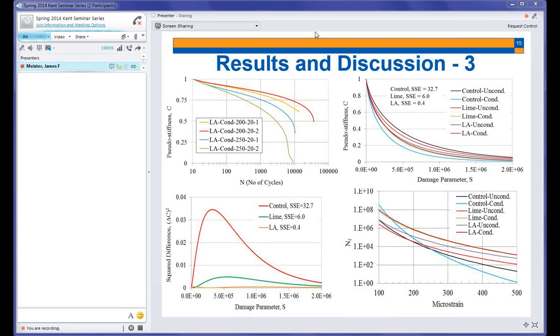Again, the number of cycles to failure for the liquid anti-strip conditioned mix, meaning it went under 5 freezing-thawing cycles, is much higher than the number of cycles to failure for the liquid anti-strip mix before conditioning. It's as if I'm saying that conditioning your mix will make it perform better, which is misleading. We know that in the field, when there are a lot of freezing-thawing cycles, the pavement gets weaker and deteriorates faster under traffic loading. This is not giving us that result.